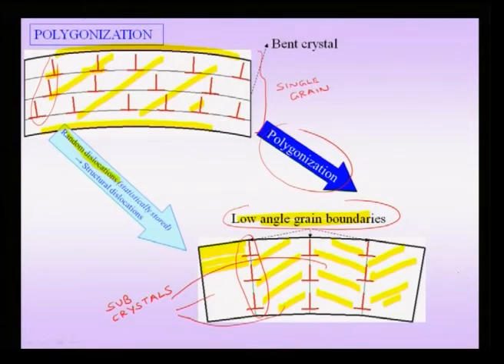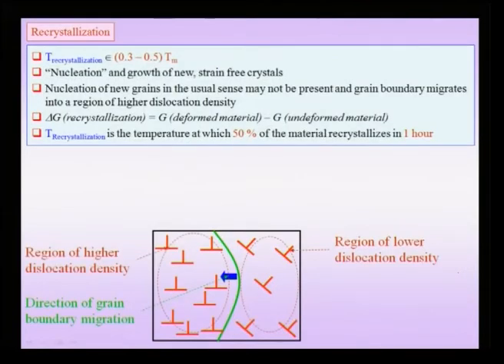That means the material still has a reasonable dislocation density, and we may end up forming this polygonized subgrain structure. Now suppose I do my heat treatment at even higher temperatures, say for instance above 0.3 Tm. So I can do my heat treatment above 0.3 Tm. Then there is a possibility that now I can refresh my entire microstructure.